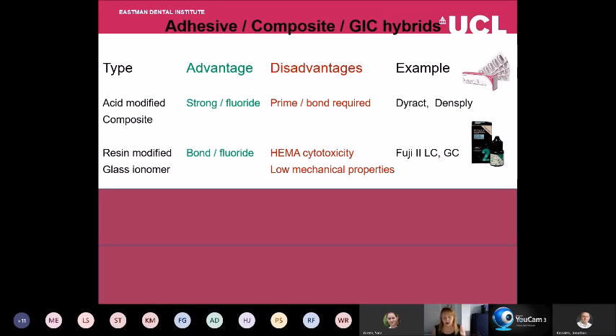Other companies are producing flowable composites. To produce a flowable composite, what you do is reduce the amount of filler. This helps the material to adapt and bond to the tooth, but you can get then a higher shrinkage with the lower filler. You tend to also often get lower mechanical properties.